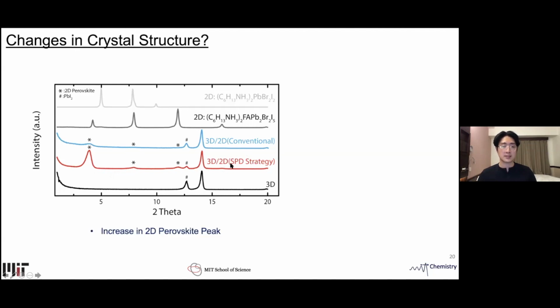Another thing that stands out is that with the SPD strategy, the diffraction peaks that correspond to the 2D perovskite, these three here, the intensity is much more intense compared to the conventional method, suggesting more efficient in situ synthesis and higher quality. We were also able to confirm its chemical composition.